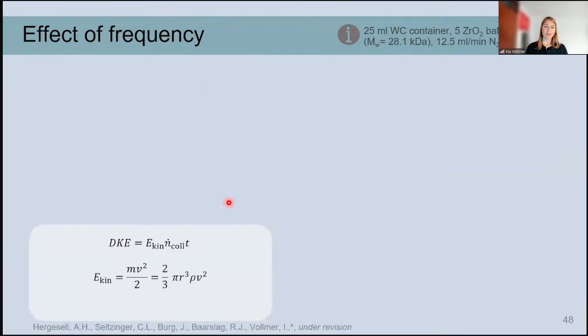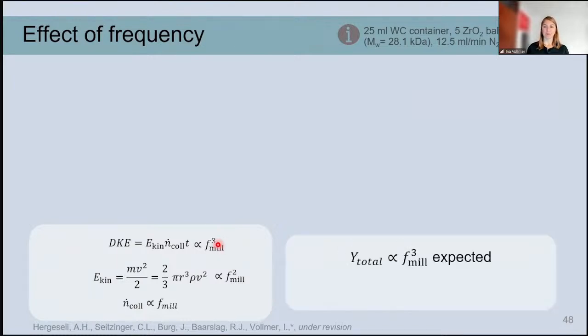And in this case, the kinetic energy is mostly dependent on the mass of the balls and the velocity. And this velocity actually is related to the frequency of the milling, so the shaking frequency. And so the kinetic energy is proportional to the frequency squared. And the number of collisions is also proportional to the frequency of milling directly. So that means that this dose of kinetic energy should be proportional to the milling frequency to the power of 3. And so this has also been done to explain the yield.